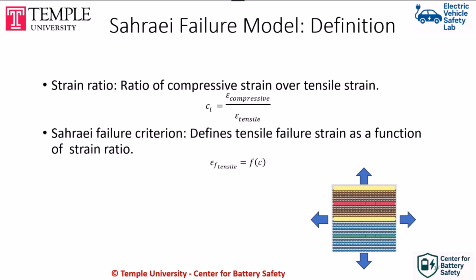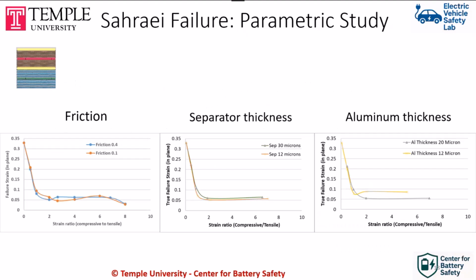So we developed this failure short circuit criterion by considering the ratio of compressive strain to tensile strain. The compressive strain is the through-thickness compression, and the tensile strain is in-plane tension. Our failure strain, which is the in-plane tensile failure criterion, is a function of this ratio. This is how the curve looks. We have done variations of changing the friction between layers, changing the thickness of layers, changing the properties, and we always get a similar characteristic curve. It is the failure strain in the in-plane direction as a function of the ratio.